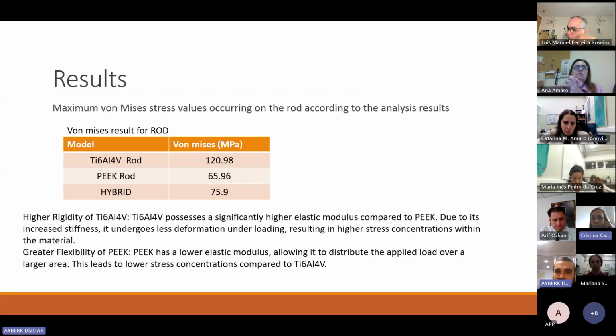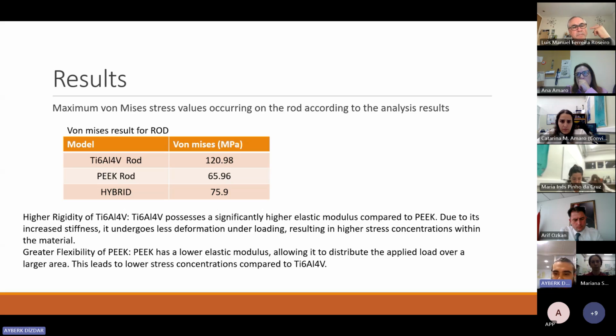Maximum stress values occurring on the rod according to analysis result. The higher rigidity of titanium alloy possesses a significantly higher elastic modulus compared to PEEK. Due to its increased stiffness, it undergoes less deformation under loading, resulting in higher stress concentration within the material. PEEK has a lower elastic modulus, allowing it to distribute the applied load over a larger area. This leads to lower stress concentration compared to titanium.